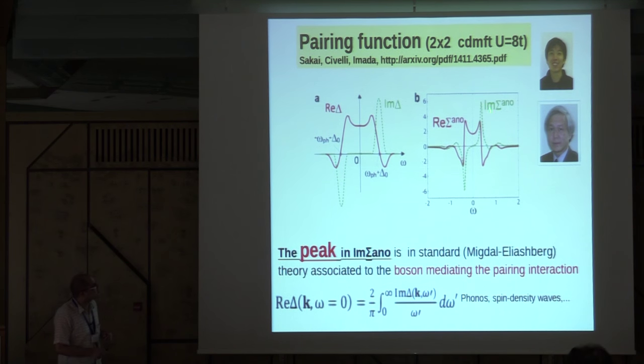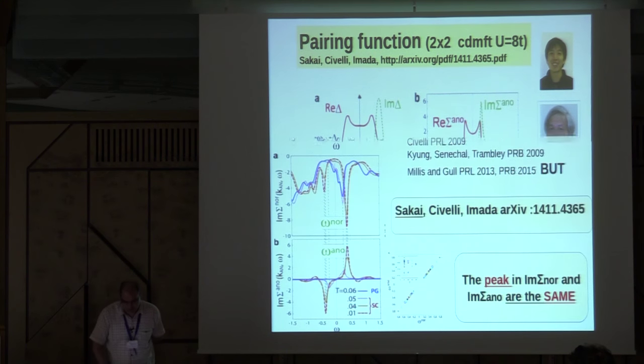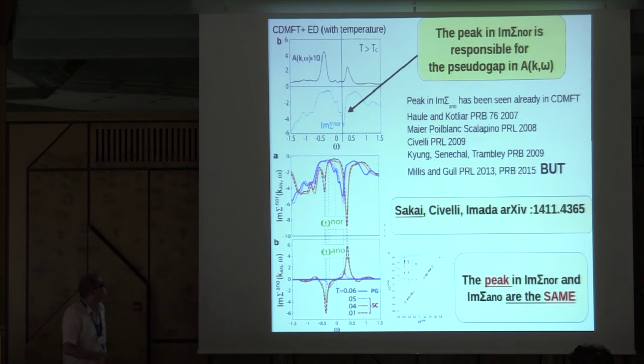Okay, why is it interesting to have these bosons, or phonons, boson peaks? Because if you look at the Kramers-Kronig relation, a peak in the imaginary part could eventually boost the gap, if the peak is closer to omega 0. The closer it is, the more the gap. And that is the main result we found. Look, this is the normal state, the spectral function in the antinode. This is the pseudogap in the antinode. The pseudogap in the antinode is a peak in the imaginary part of the self-energy.